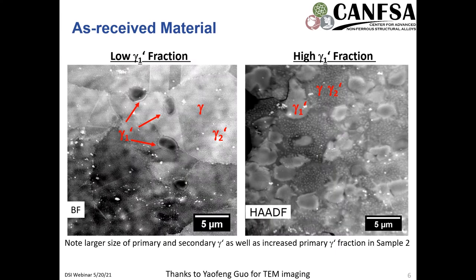For this project, I was provided with two pieces of material. We have here on the left a low primary gamma prime fraction, and on the right a high primary gamma prime fraction. Should note that these are the same alloy, so the phase fraction net of the gamma prime is the same. It's just a different distribution between the fraction that exists as primary gamma prime versus secondary gamma prime.